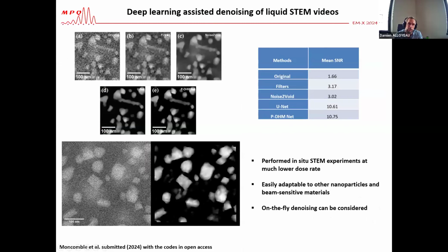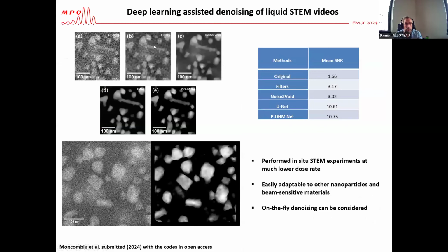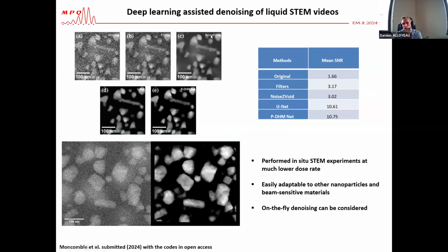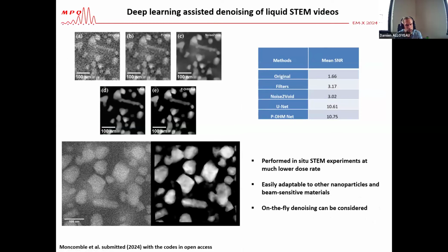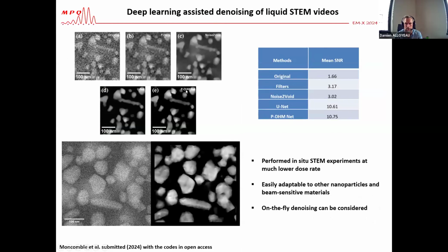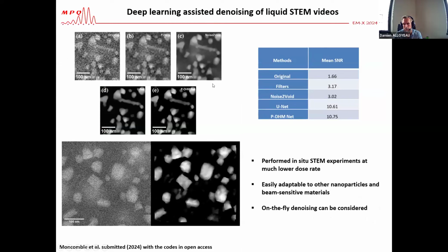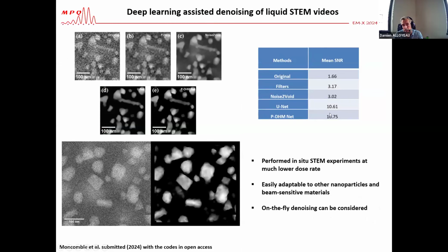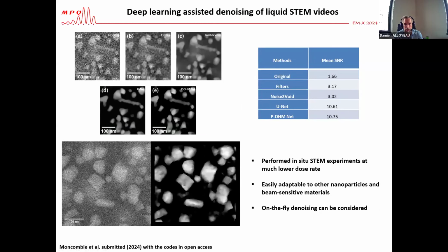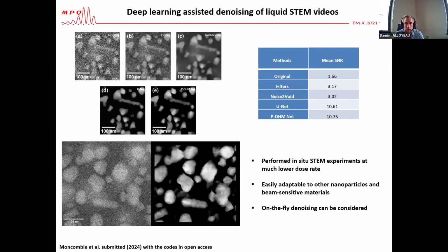Here I show you a comparison between an original image, what you can obtain when you apply conventional filter strategies, what you can obtain with the Noise2Void deep learning approach, which is a neural network that is trained only with noisy images, and this is our approach using a UNet, specially designed UNets developed by one of our collaborators at EPFL. And you see that in terms of image quality and signal-to-noise ratio, our approach is definitively better than other conventional methods to denoise liquid cell TEM images.